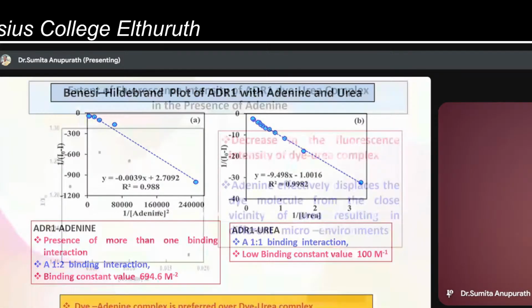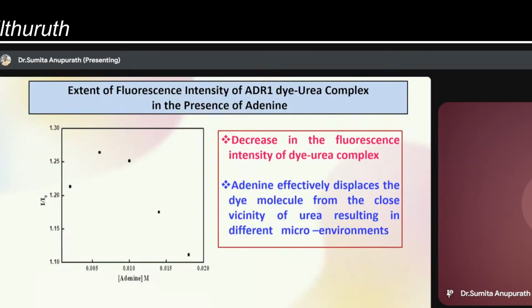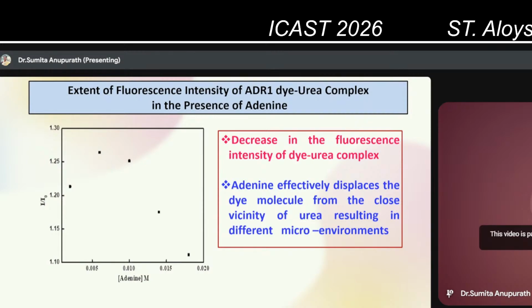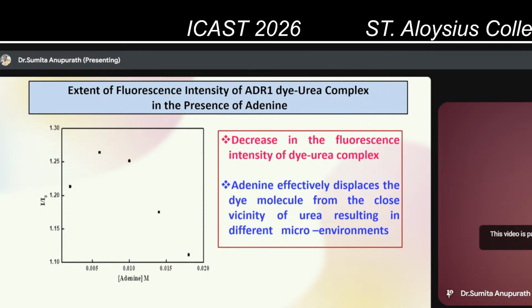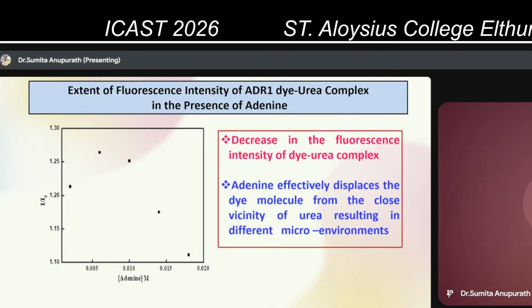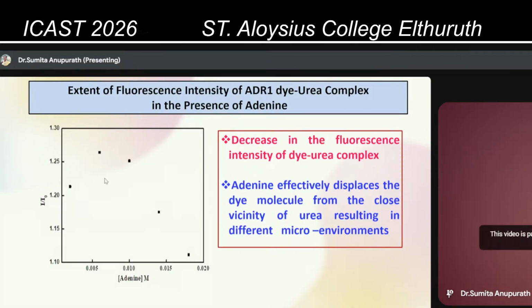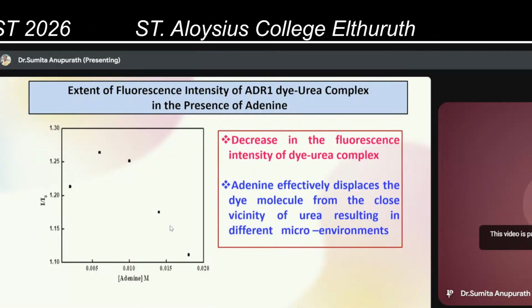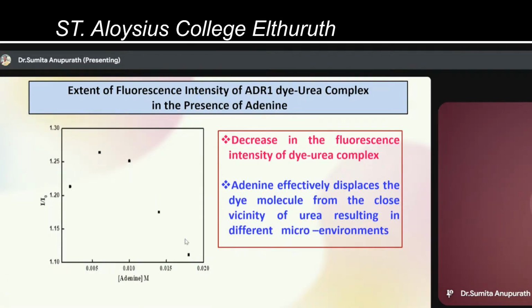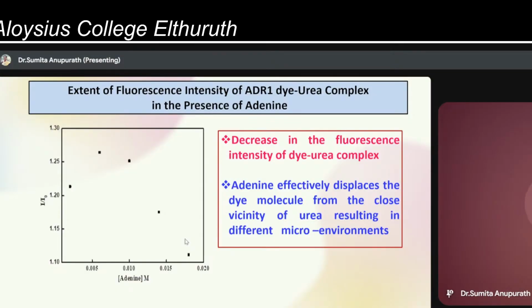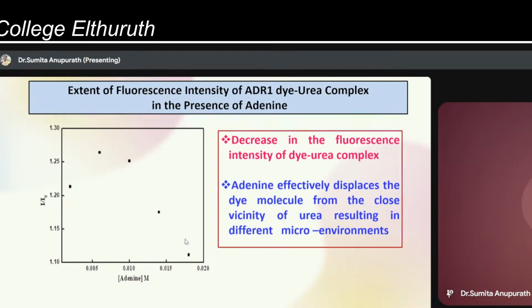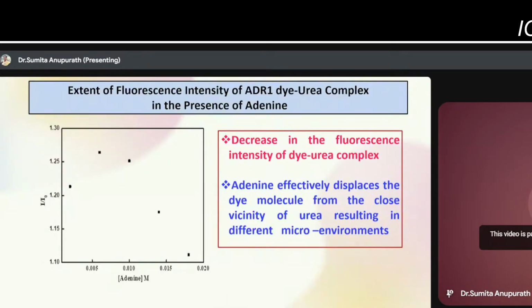Further, again to emphasize the stability of the dye-adenine complex, we measured the fluorescent intensity of the dye-urea complex in the presence of adenine. That is, we added adenine at various concentrations to a dye-urea system. And we found that with the increase in the concentration of adenine, the fluorescent intensity decreased, which shows that adenine was able to effectively displace the dye molecule from the close vicinity of the urea and itself bind with the dye. As such, it resulted in different microenvironments.